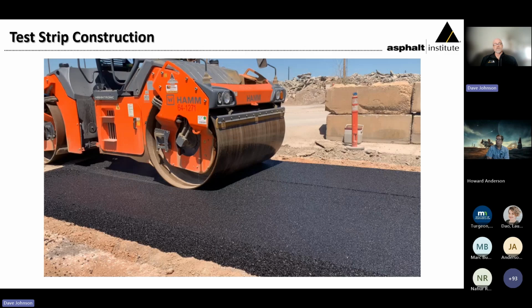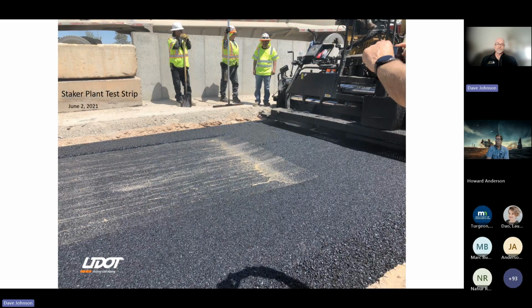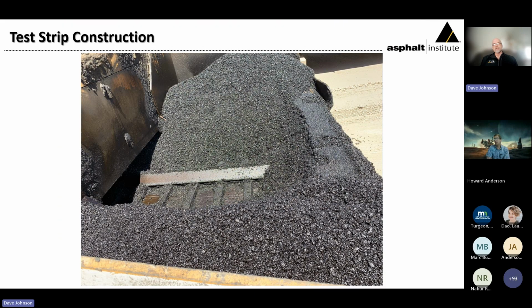The test strip construction went without much of a hitch. Compaction was done with a single double drum vibratory roller, as we see in this picture. Just an example of what it might have looked like after an initial pass. I have to say that my one regret is I don't have any pictures of the roller hanging off the edge of this mix. We all expected it to walk out a little bit. It was shockingly stable. Not too much of a surprise when you're trying to pave at this thickness.